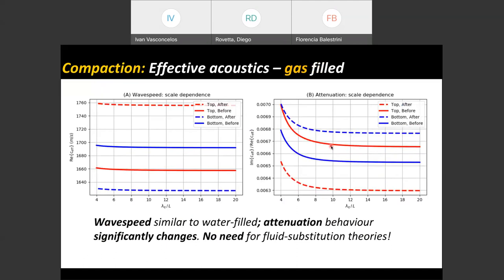We did not use any of the existing fluid substitution theories. All we used here is our knowledge of the properties of the fluid and of the geometry of the material. So all we did here is to show you the dependence of the effective properties as a function of frequency with microstructure. The other thing I want you to remember, and we can discuss this at the end, is that this dependence on frequency exists at a specific range of frequencies, and then it flattens out.